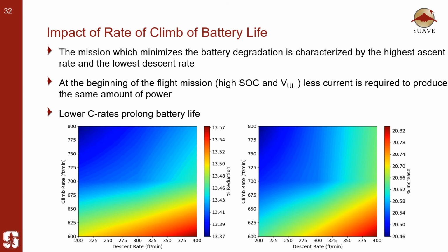Initially, at the beginning of the mission, at high SOC and open circuit and load voltage, less current is required to produce the same amount of power required by the propellers. As a result, since the current is less, if you remember the equations of the battery aging, particularly the cycle aging parameters, which depend on the charge throughput, the small currents will reduce the charge through the battery, and as a result, the aging is less than at low SOCs where higher currents are required.